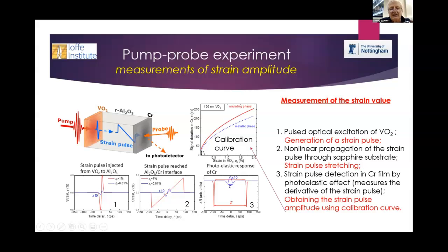So what pulse is injected, and what happens some time later when the strain pulse approaches the chromium film - eventually, because the pulse is reflected from the surface, we measure two sharp pulses, and this time delay is related to how the pulse was stretched. We may calibrate this time, and from measuring it quite precisely, we know the strain amplitude injected into the crystal - from vanadium dioxide into sapphire.